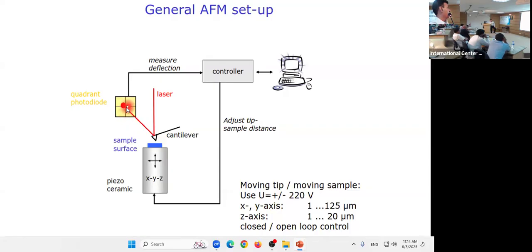This red spot should be in the middle. So when the cantilever is moving here and there, the light which is coming here deflects and lands at a different position. That deflection goes to a controlling system, and that controlling system is sensitive and recognizes this whole system and the activity here. In that case, an image is created, and that is what we see in our daily routine analysis.